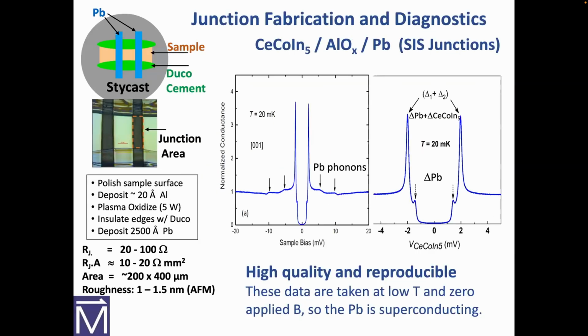I'll do that now. So I'll show you this right here: what we have here is cerium cobalt indium-5, aluminum oxide, superconducting lead as the counter electrode. And here, as we expect, we see the lead phonons. We also see the cerium cobalt indium-5 plus lead gap, because this is delta 1 plus delta 2. And so we know that we have really high quality junctions. Once you have a junction of this high quality, what we did in high TC is bring it up to 10 degrees, or what we can do in cerium cobalt indium-5, put a couple of kilogauss on it, and cerium cobalt indium-5 with several Tesla HC2 doesn't give a hoot. So you make really good tunnel junctions. You just change a little bit. So the counter electrode lead is now the normal metal. So you have cerium cobalt indium-5, insulator, Fermi liquid that you're tunneling to, normal metal.